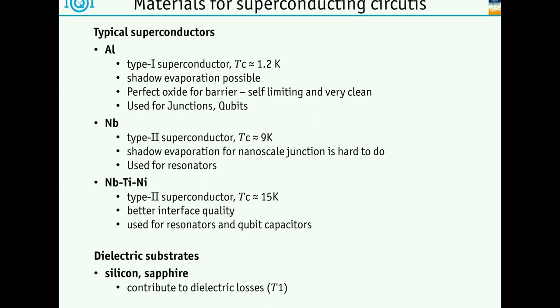This is the best barrier we know how to make, this very thin insulating barrier between the two superconducting halves. And so with that, it's very easy to create a junction. I'll tell you in a little bit, we use this shadow evaporation technique to create junctions. So aluminum is typically used for qubits and junctions. Niobium is quite nice because it has a somewhat higher transition temperature. It's typically used for coplanar waveguide resonators.